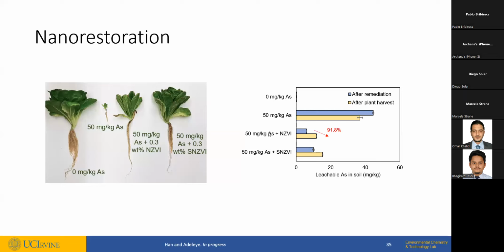However, when the soil was treated with the nanoparticles, we saw the opposite trend, in the sense that after the plant was harvested, the leachable arsenic increased both in the NZVI and the SNZVI treatment system. And we think that will be due to the effect of the root exudates released by the plant. And we need to start another study to test that hypothesis. But here's what we found so far.